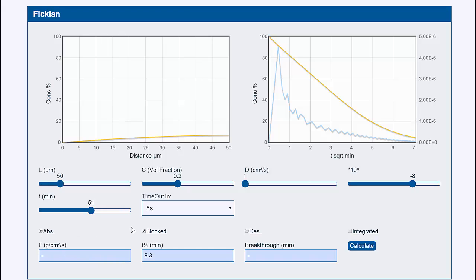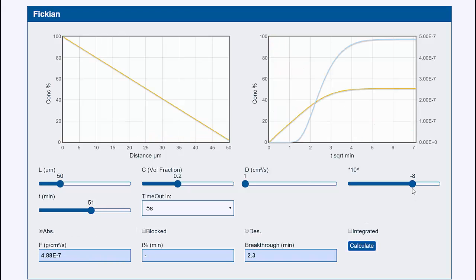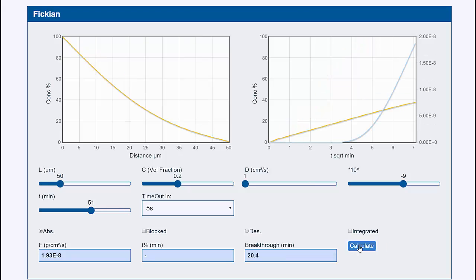For example, let's go back to absorption — a familiar curve. If we go to a more crystalline polymer, then its diffusion coefficient might be 1×10⁻⁹ instead of 1×10⁻⁸. And of course we have a big difference in the amount that gets through. Enjoy playing with the modeler to get a feel for what this basic Fickian diffusion can do.